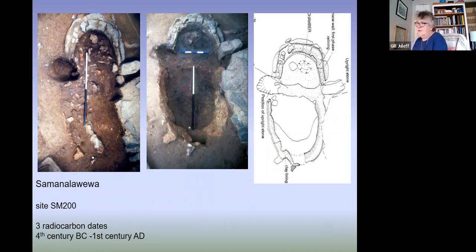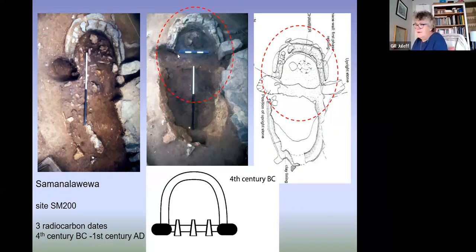But if we look closely at this furnace, we can see similarities. We have a structure, albeit somewhat smaller, where we have stones connecting a curved furnace wall, a clay wall. This stone has been robbed out, with a straight wall across the front. We know from the debris that came from this furnace, it had multiple tuyeres. And if we simplify this furnace into this schematic footprint, this is what we're looking at: 2 stones, a back wall, and a straight front wall.